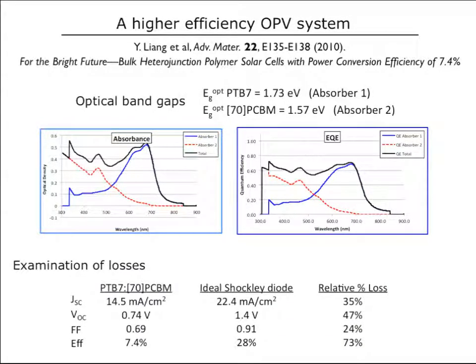So we can do a little bit of thermodynamic analysis on this system and see where the losses are. First of all, we can look at the band gaps of the two materials. We have this PTB7, the polymer, which has a band gap of about 1.7. And then the C70, band gap of about 1.6. So approaching the nominal optimal of 1.4. Now importantly, the C70 is not a very good absorber. Its spectrum is given here, but it's only a relatively small portion of the spectrum relative to PTB7. So this is the total EQE. Its average is about 60% from up to about 800 nanometers.